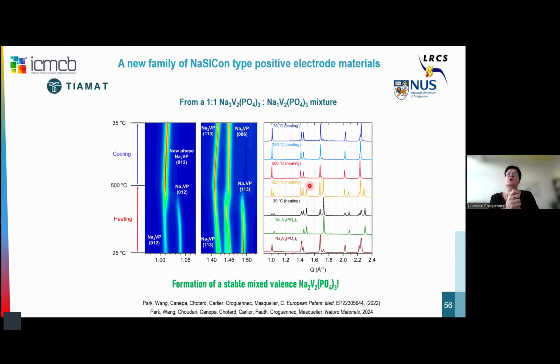Of course, we were interested to stabilize and to search more around these materials, Na2V2(PO4)3. It's interesting because here we have a mixed valence for vanadium, V3+ and V4+, and we have only 2 sodium per formula unit, so I would say deficient sodium. And in fact, we did this chemistry here, mixtures between Na3 and Na1, and we did it in temperature, in synchrotrons, and you can see that we move from 2 phases to a single phase, but when we cool down, on the contrary to what we had in the battery, we maintain a single phase that is stable at room temperature.